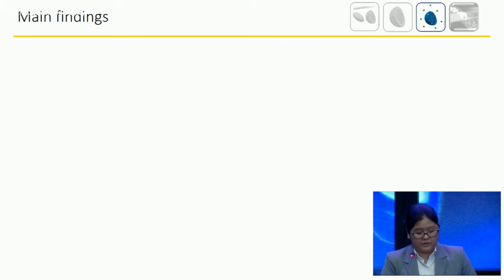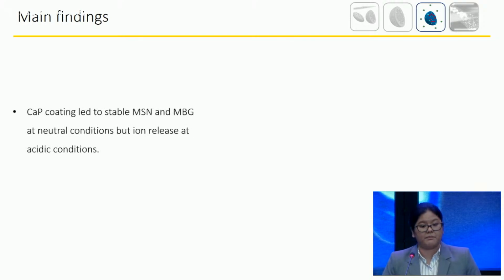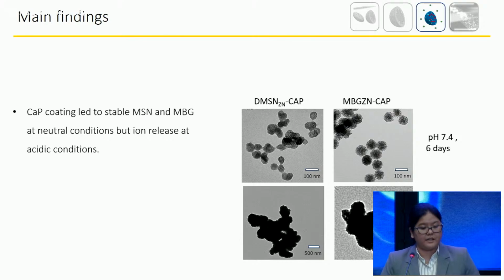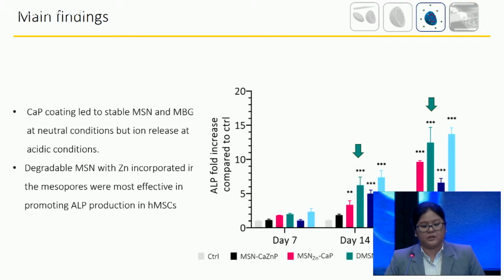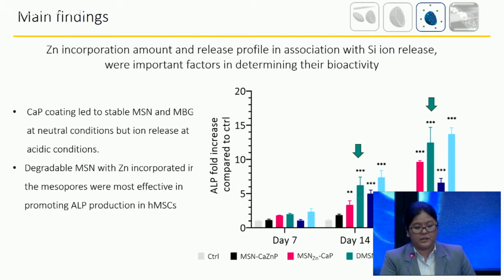We demonstrate that the calcium phosphate coating leads to stable MSN and MBG at neutral condition, but stimulates ion release at the acidic condition. Moreover, degradable MSN with the zinc incorporated in the mesopore were more effective in promoting ALP production in HMSC. Therefore, the zinc incorporation amount and release profile in association with silica ion release were important factors in determining their bioactivity. As such, these factors should be considered in the design of therapeutically active ion-doped silica nanoparticles.